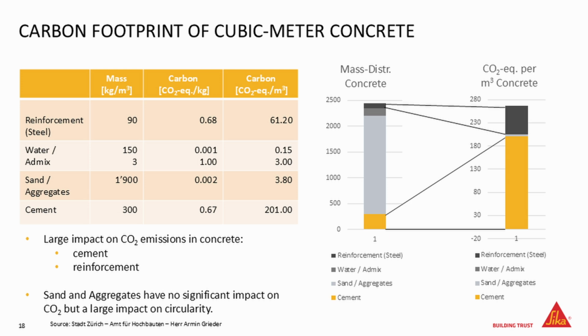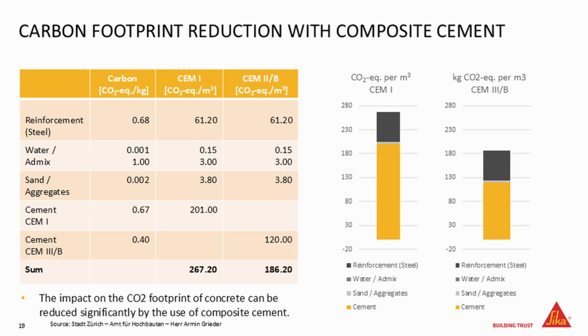So coming back to the city of Zurich, what did they do? They said, okay, we look at the cement, and we now look at alternatives to a pure Portland cement. When we look at the CO2 equivalent of a composite cement, we see we could save a lot of CO2. A CEM 3B has a much lower value in CO2 equivalent per kilogram than a Portland cement, and with that, they could reduce the CO2 footprint per cubic meter of concrete significantly.